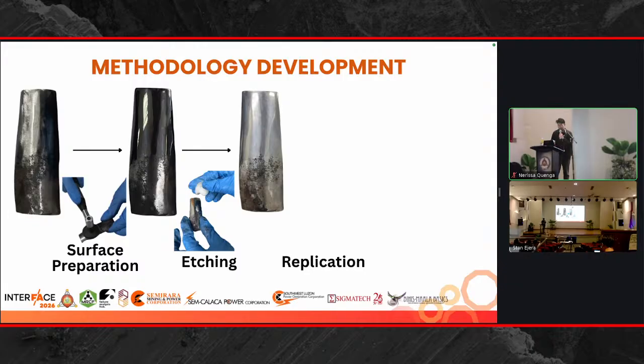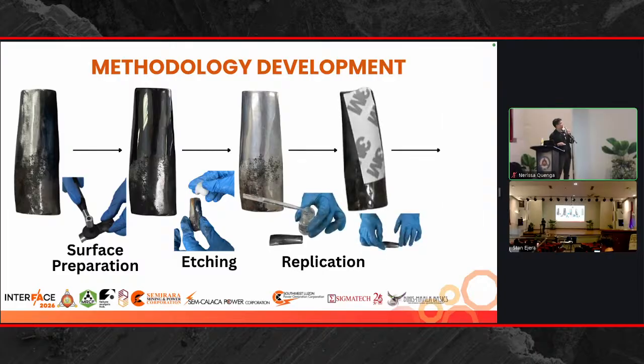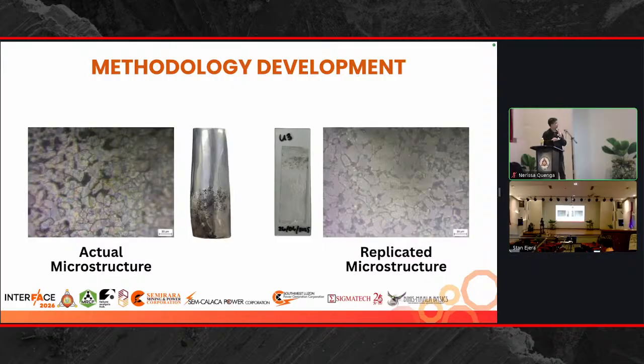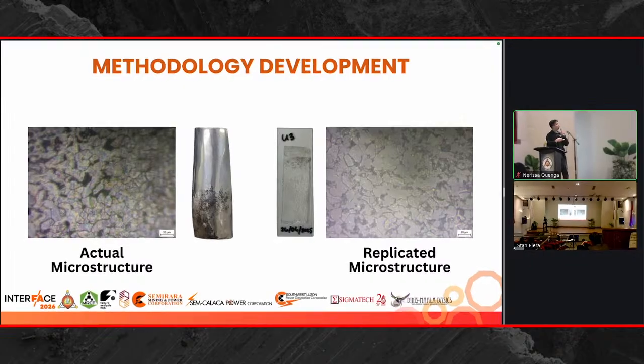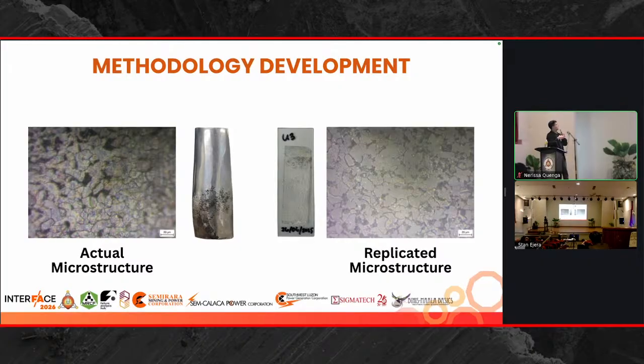So the general idea here, let me show the final replica sample that we acquired. The replicating agents, the acetone and the cellulose acetate film, copy the surface topography of the etched part so that it can be analyzed under the microscope once the replica sample is extracted. As seen in the figures on the slide, these figures show how the actual microstructure, taken from the metal sample itself, and the replica, acquired from the cellulose acetate film, differ. We can see that although there's somewhat less clarity in the microstructure here, it was still able to replicate the general microstructure in the actual etched sample.